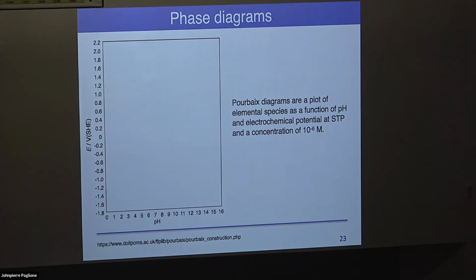So how do you construct a Pourbaix diagram? Again, it's electrochemical potential as a function of pH. Because this is only one slice in that 3-dimensional concentration plot, most Pourbaix diagrams take a concentration of 10 to the minus 6 molar, which for most of your systems might not necessarily be the case. But if you start to be worried about concentration playing a large role, you can start to include that 3rd dimension.